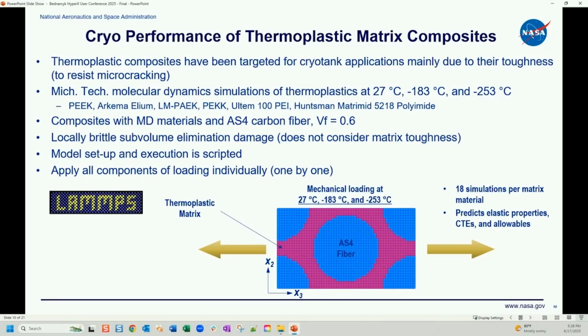So this is a slide on the micromechanics simulations, just real quick. The reason we did this is because, even though the finite element model is simple, we wanted to make it as representative as possible. So we wanted to use properties at the different temperatures. The material properties for thermoplastic composites aren't available at all those temperatures, but it just so happened that Michigan Tech had a project with NASA Langley, actually, where they were using molecular dynamics to predict the properties of the neat thermoplastics, 6 neat thermoplastics at cryogenic temperatures, room temperature. I think that's liquid nitrogen, and that's liquid hydrogen temperatures. So by using this, if we could then get ply properties using these, we could have all the properties we needed available, and also it's a pretty good one-to-one comparison among the materials, since they were all generated this way.